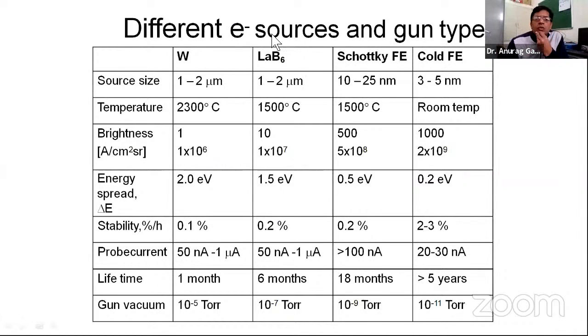So this is the table of the different types of guns being used for these systems, like tungsten. What is the source size? Then LaB6, lanthanum hexaboride, Schottky field emission, cold field emission. So this is the source size. Then how much temperature they generate. Then the brightness, and the energy spread across the beam. And the probe current, and their gun vacuum, that is, how much vacuum is required in these guns. In Schottky and cold field emission, they need 10 to the power minus 9 torr or 10 to the power minus 11 torr.